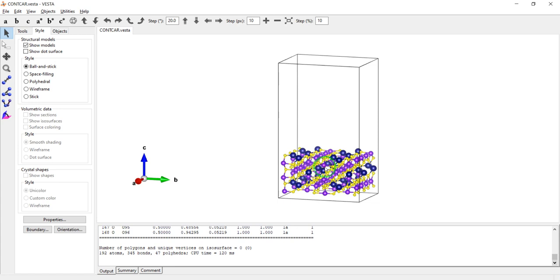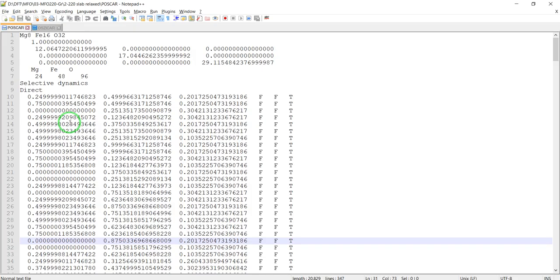The first change is the mesh density, which is obvious because the volume of the unit cell has changed and you have added some vacuum layer, so you need to change the mesh density first. The more important part is selective dynamics. Since we want just the surface atoms to be relaxed, we should fix the position of at least one bottom layer.